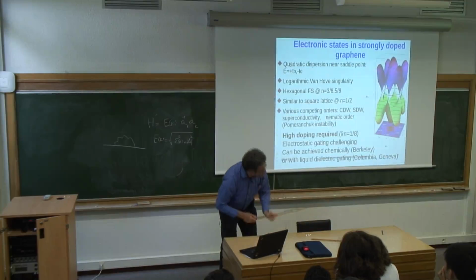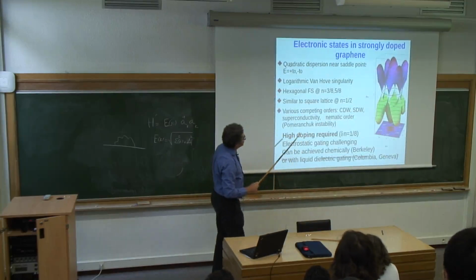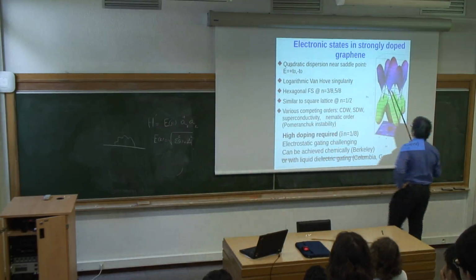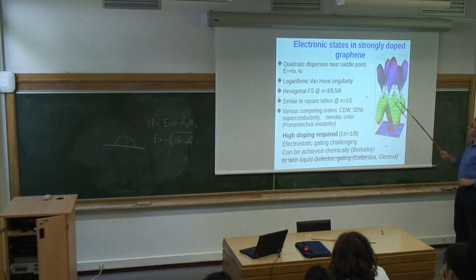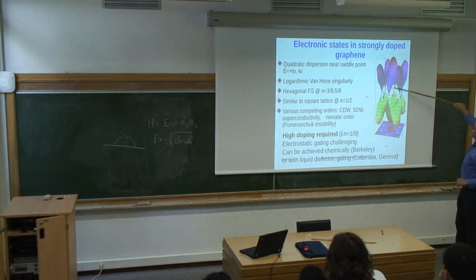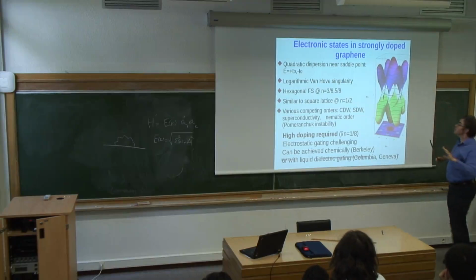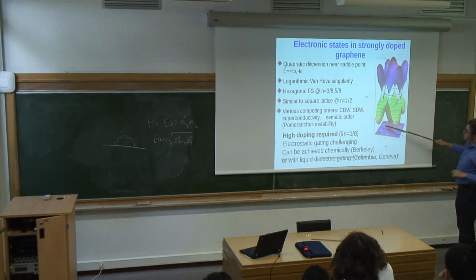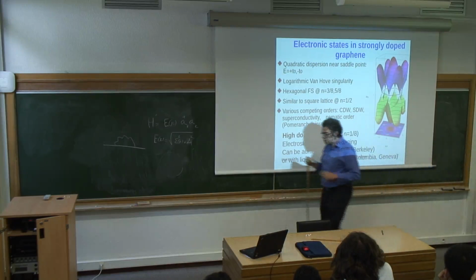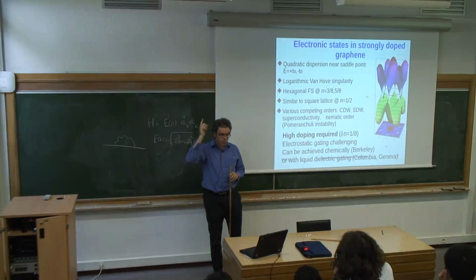Right. So if you take graphene band structure and look at it on a larger scale than we did so far, then there are saddle points over here, which are somewhere between this hill and that hill. So they look like mountain passes around us, right? And you may see it better in projection, if you draw a contour plot, then the contour plot will look like this, and there are these saddle points. So saddle points are interesting because density of states there is divergent because of Van Hove singularity, and so people